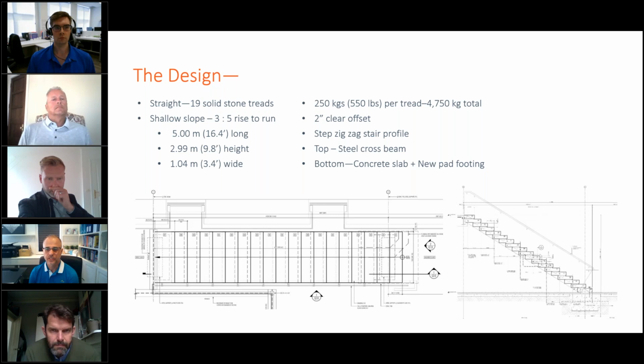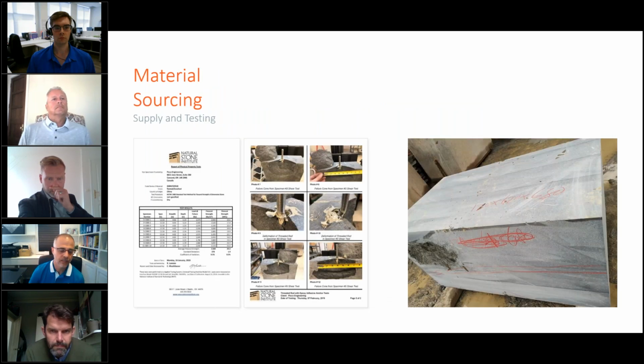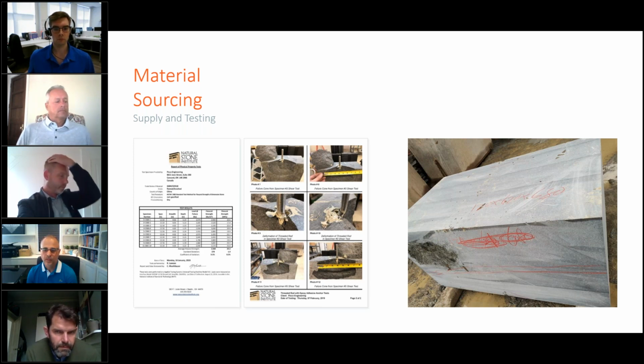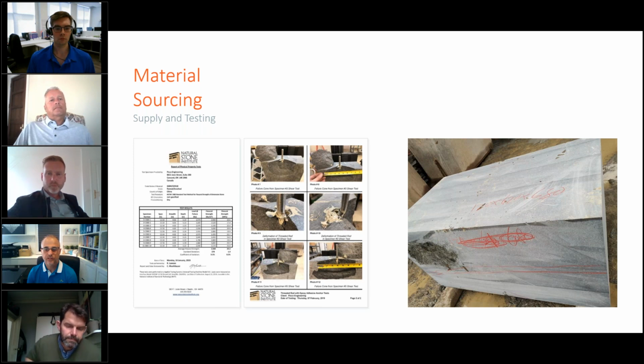So, material sourcing. From the outset, sourcing was a challenge. The G684 basalt was a Chinese government controlled material and supply was low from various quarries we contacted. We were lucky to find the material we needed after multiple sources fell through, but it was critical to understand what we had found. We did our own ASTM testing of samples prior to purchasing the full quantity. C97, C170, and C880 tests were done by the NSI lab in Ohio.